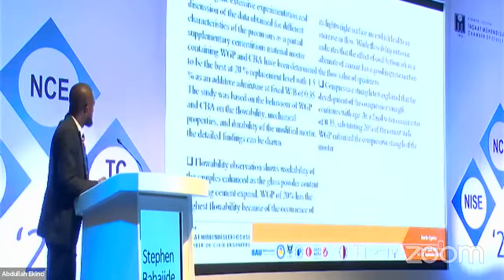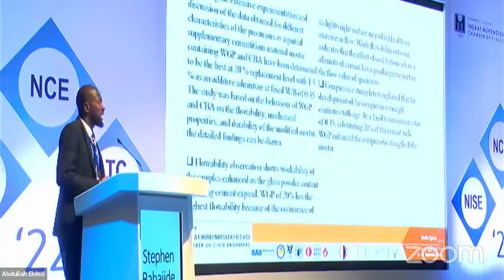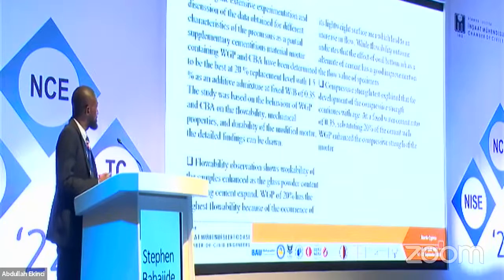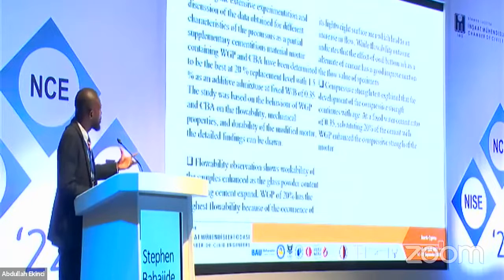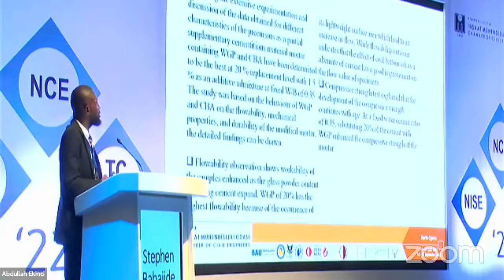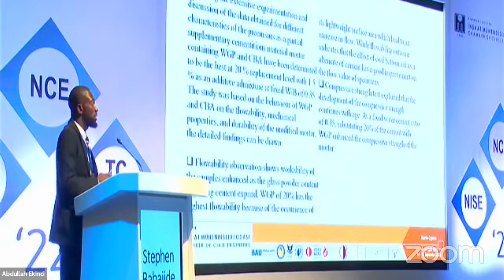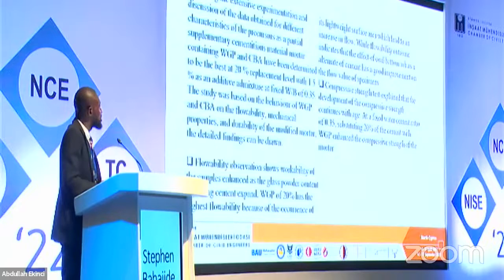In my conclusion, it is noted that waste glass powder has been determined as the best at 20% replacement with a level of 1.5% of additive and a constant water binder ratio of 0.35. And in my conclusion, flowability observation shows that workability of these samples enhanced as the glass powder content replacing cement expanded. And also, the compressive strength shows that development of strength increases with age at a fixed water cement ratio of 0.35. Substituting 20% of cement with the waste glass powder enhances the compressive strength.